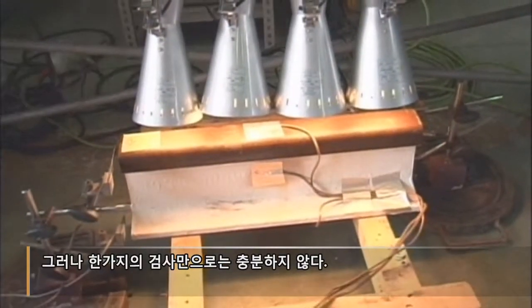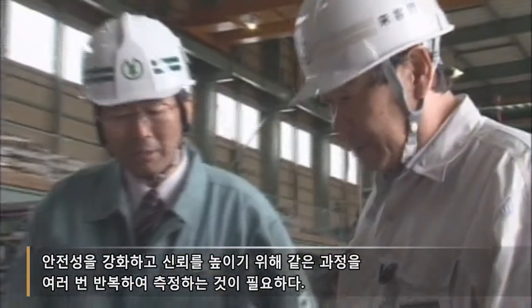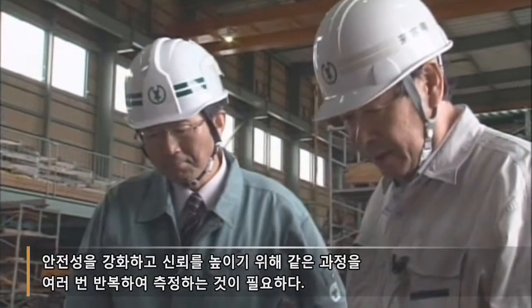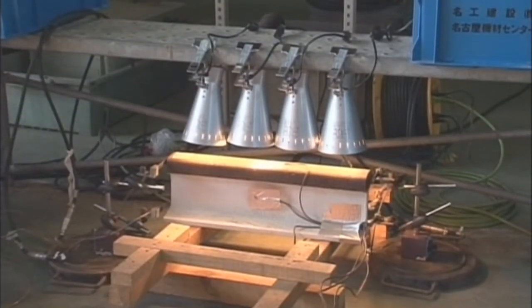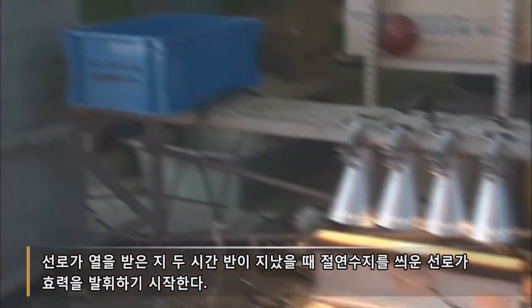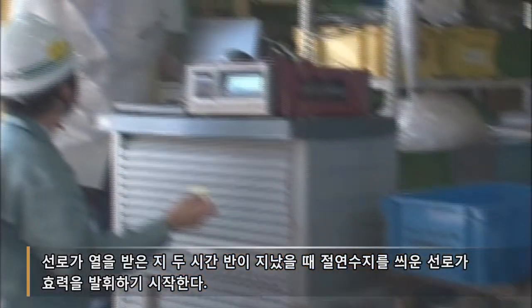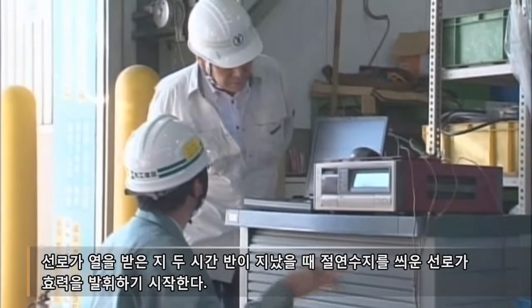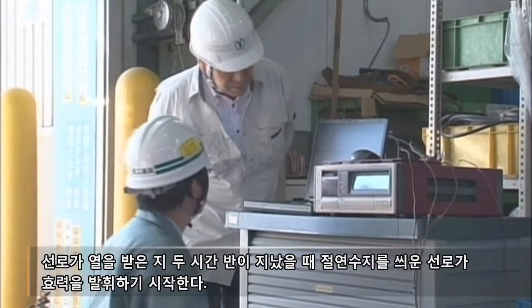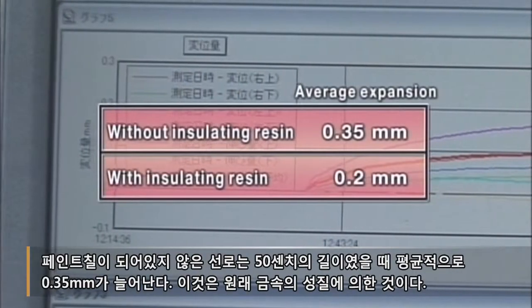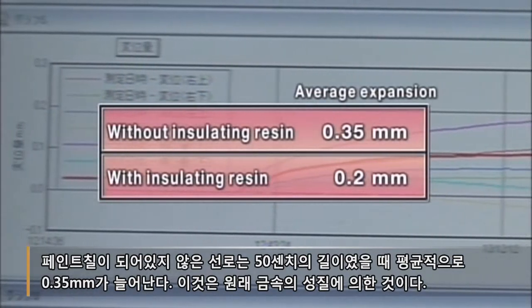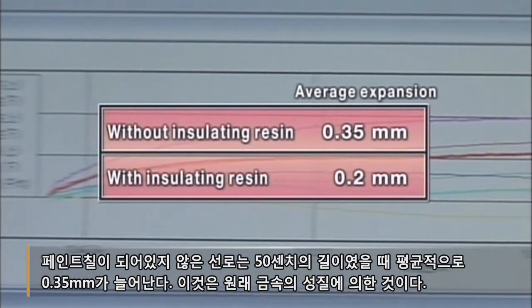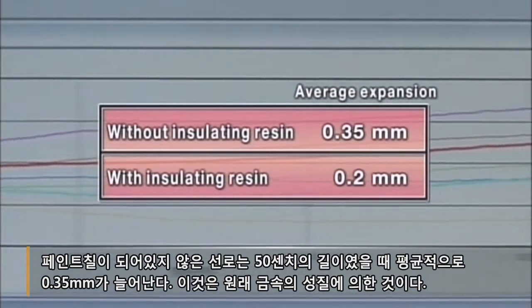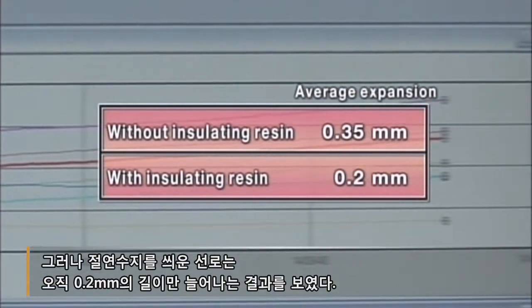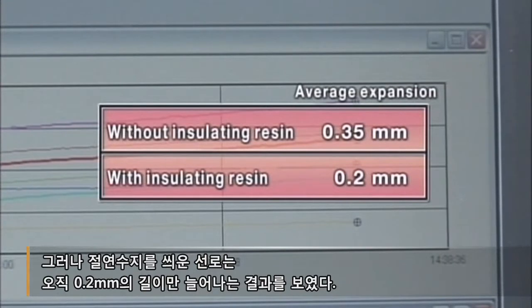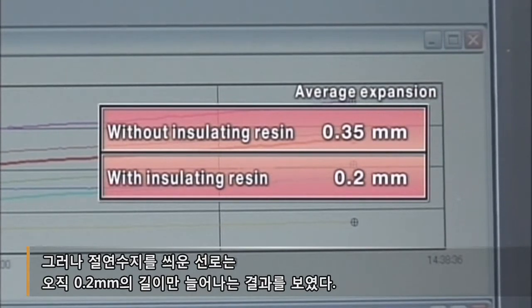But one test is not enough. They need repeated results to prove reliability. 2.5 hours after the rail started to be heated, the measurements show the insulating resin is having an effect. Without the paint, a 50-centimeter long segment expands by 0.35 millimeters on average. That's about the same as the original steel. But the rail with the insulating resin has only grown 0.2 millimeters.